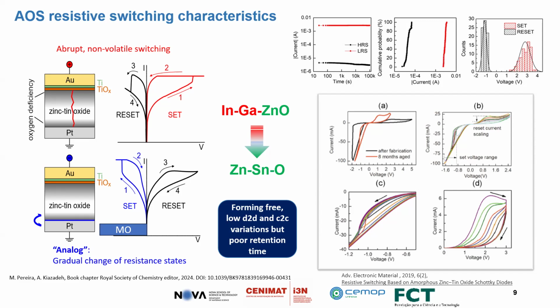We noticed that if we exchange the platinum with molybdenum, we can actually have the same material as our transistors, like gate, drain and source electrodes, the same material, the same electrodes, and at the same time we can again duplicate the same resistive switching properties: analog, gradual change of resistance state, and area-dependent device, as shown in this figure. So you can have a very nice analog behavior based on changing the current state in the set or stopping the reset voltage at different points, and different resistance states can be achieved.